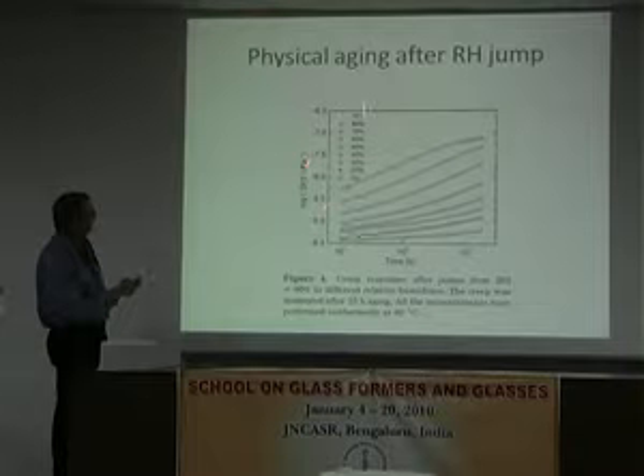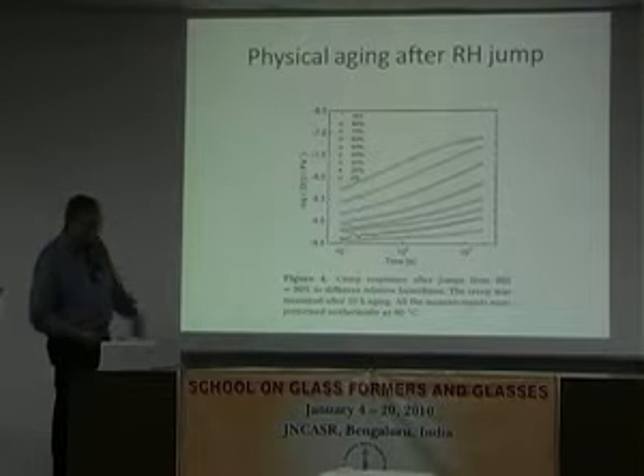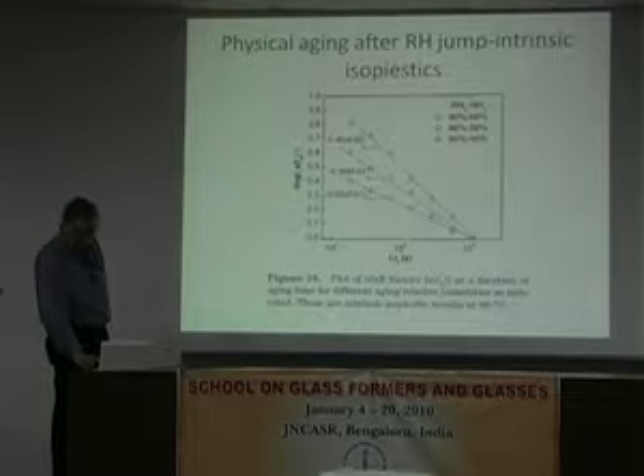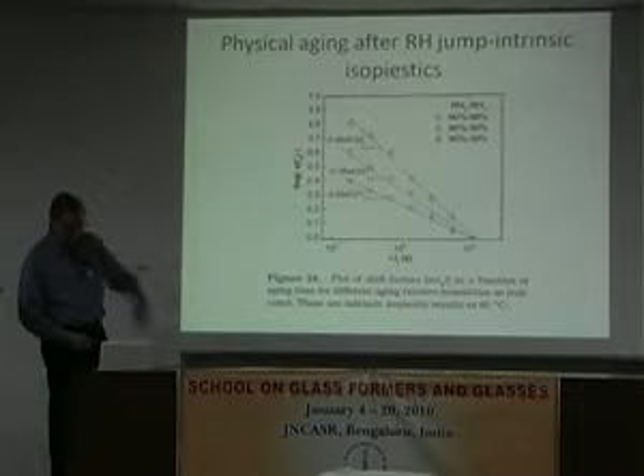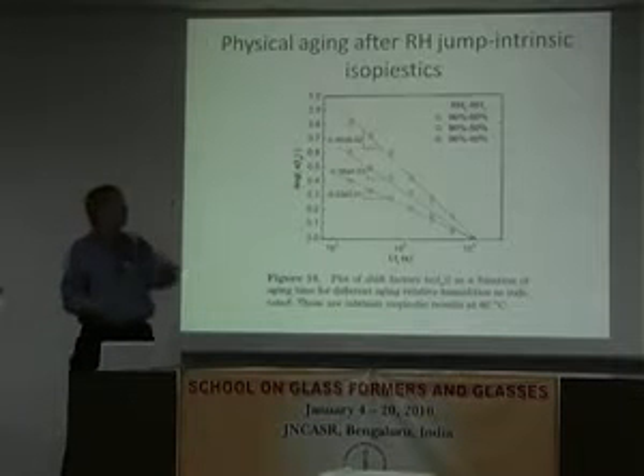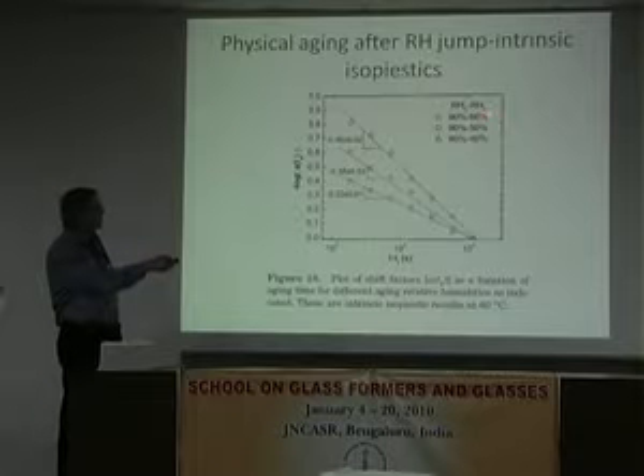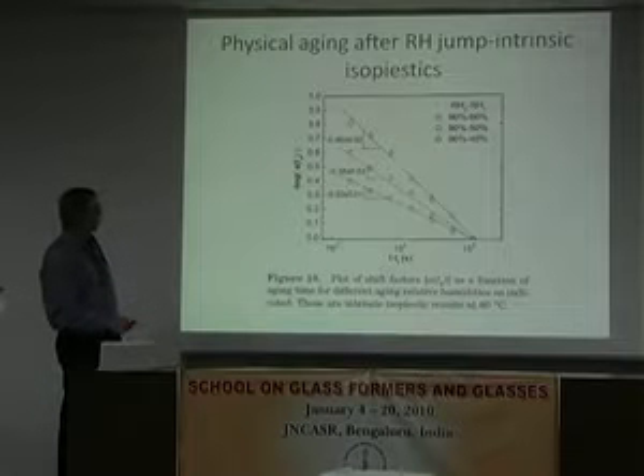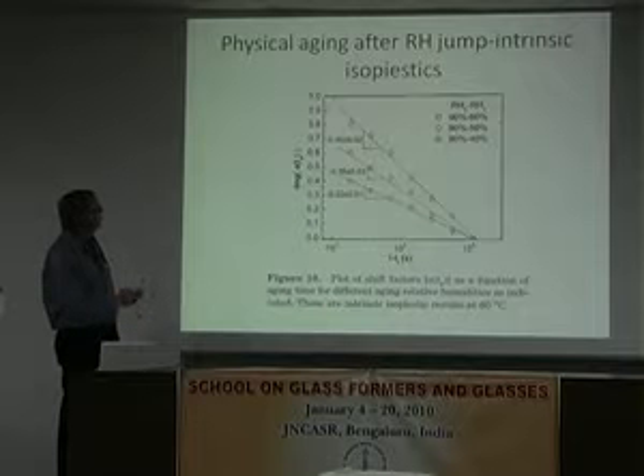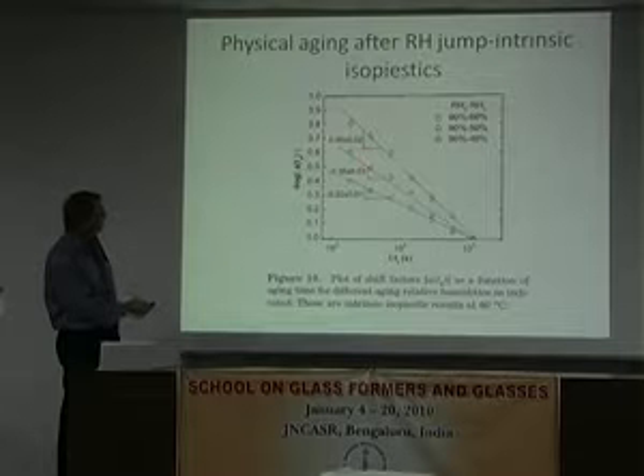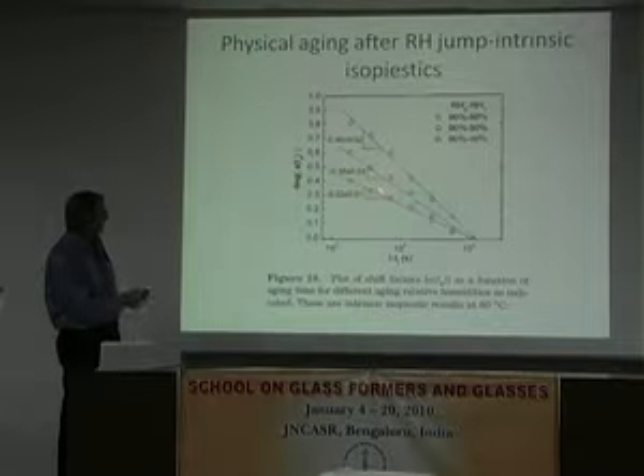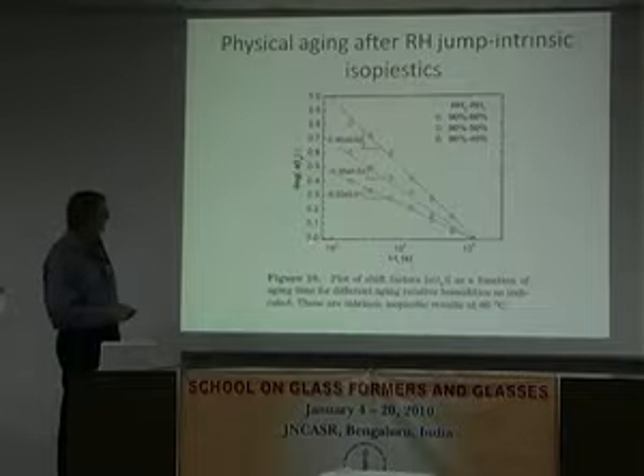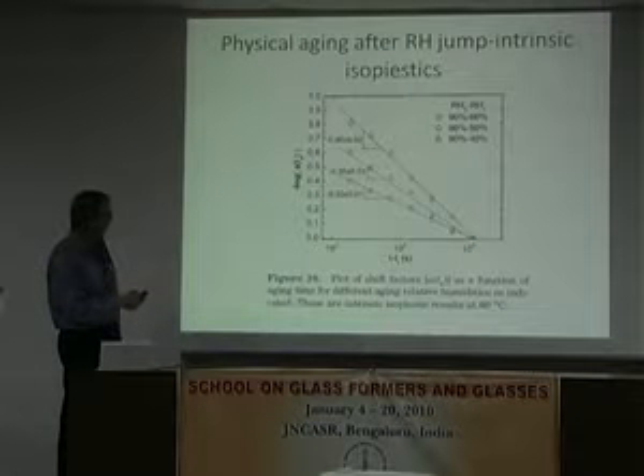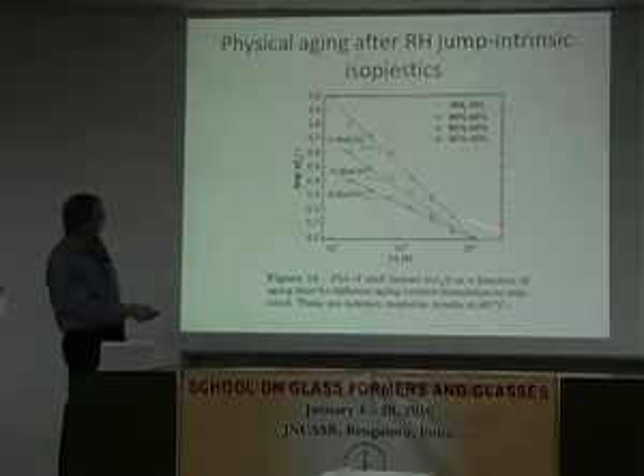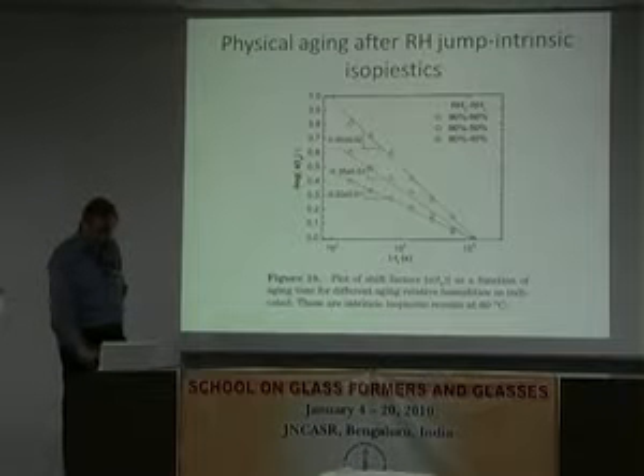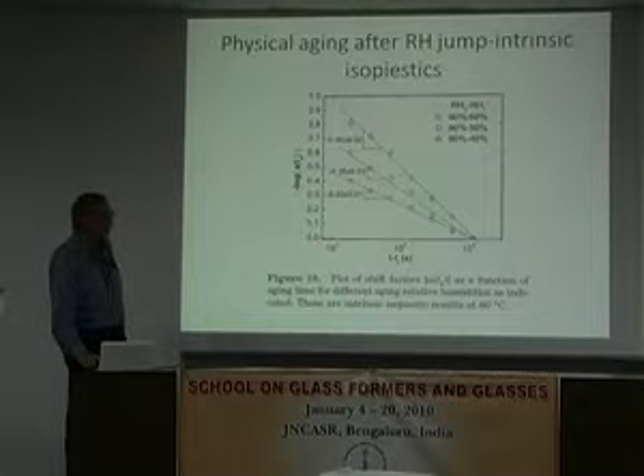We did it at different relative humidity, so you get time-humidity superposition. And then this is the intrinsic isopiestic, so we do a down jump from 90% to 60% relative humidity at 60 degrees centigrade for this material. And you see this looks sort of like the intrinsic isopiestics. Okay, so we get down to whatever the shift factor is. And in this case, we're getting straight lines. So that's like we would get with the temperature in this regime.